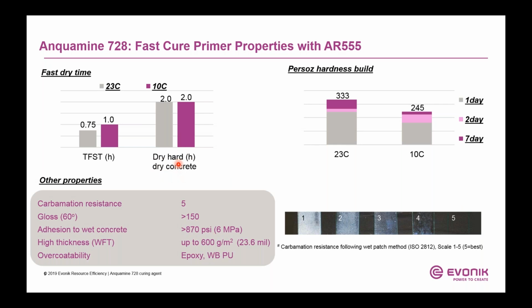On dry concrete, at 10C and 23C, the temperature doesn't show any effect on the dry speed, and the primer has a thin film set time within 1 hour. The primer also has a very fast property build up within 1 day, going up to 7 days. That just shows the hardness build. In addition, these are the other key properties of Anquamine 728 primer. It has excellent carbamation resistance. So here is a scale of carbamation resistance. Good carbamation resistance is a requirement for good intercoat adhesion to the top coat, since this is a primer.